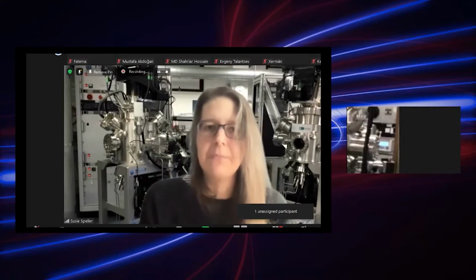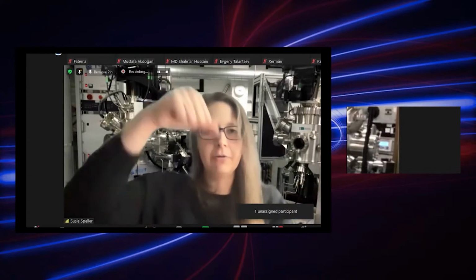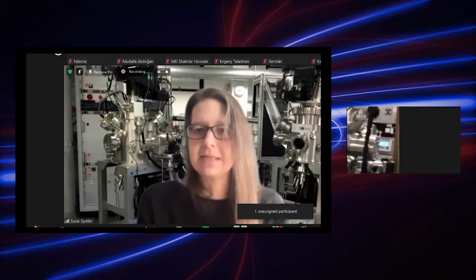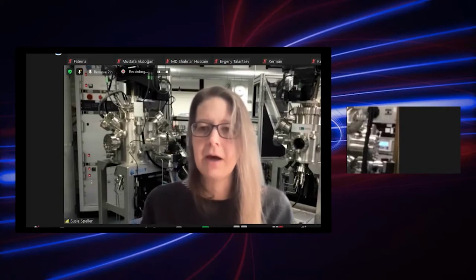How did you apply the huge 5 gigapascal pressure? Is that during the sintering? Yes, so the 5 gigapascal pressure was done at Element 6 using their industrial cubic presses. So you press from all directions whilst you're heating. So that's the process that we use.